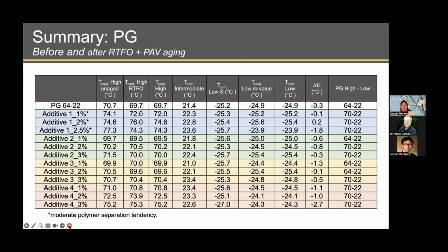And here we have the summary of everything that was presented in the graph. So what was presented in the graphs is completely included here in this table. As you can see here, on the last column of this table, we have the final PG classification of the modified asphalt binders. You see that the base binder initiated at 64-22. And when we incorporate additive 1, we had an increase on the higher temperature performance grade to 70.